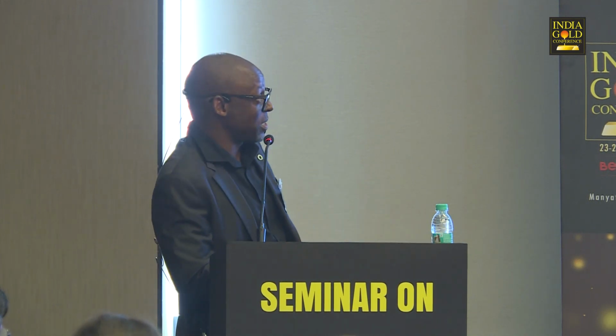And then we've got high purity bars. Some of the high purity bars, mainly some of the guys use drill samples that I'll talk about in one of the investigations that we did. So all these get to be dried. We've got an induction furnace. I'll mention the importance of having an induction furnace compared to a melting furnace, whereby we take samples and then roughly we take about 8 dips and 4 discs. And then this is for a small average size deposit.